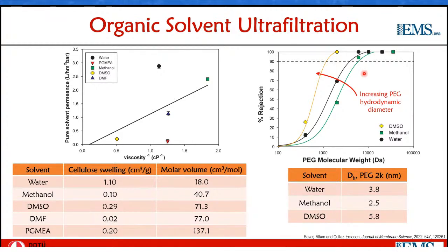This does not relate to the membrane solvent interactions as we see from the swelling, but it seems to be related to the hydrodynamic diameter of the probe PEG molecules that are different in these solvents. So here you see for one of the probes of 2 kilodaltons that the size is the largest in DMSO, followed by water, and then followed by methanol, which explains the molecular weight cutoff order of these membranes in these 3 solvents.